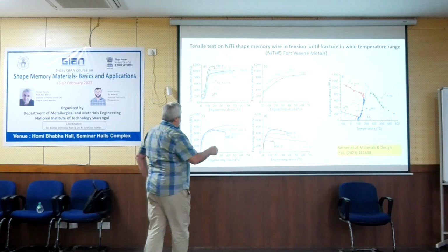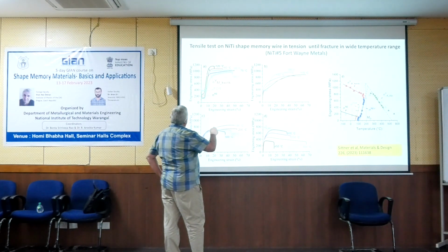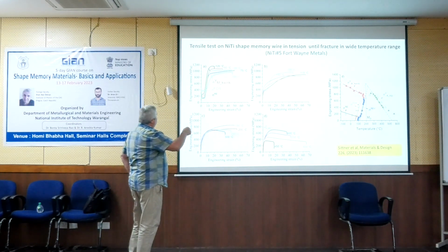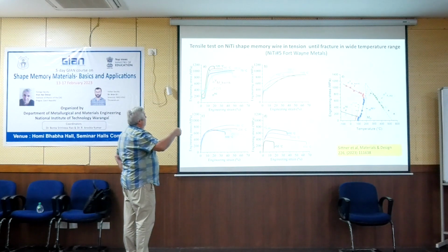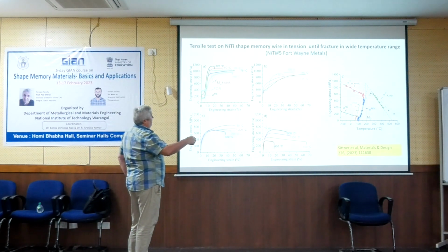This is because at high temperature some plastic deformation already proceeds. Here it was elastic only. But at high temperatures, the martensite starts to deform plastically, and you will get this change. But this flow, this plastic deformation range will be at similar stresses, around 800 megapascal. Still, you will climb out to this level.